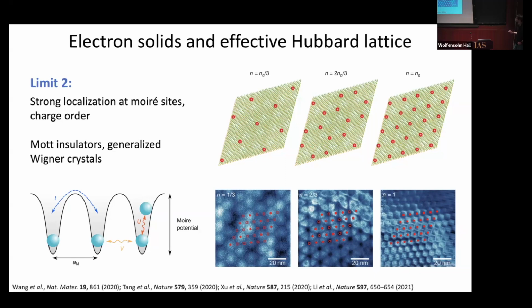That terminology comes from the fact that, just like in a Wigner crystal, this electron solid is stabilized by the long-range Coulomb repulsion. But on the other hand, here you have a Moiré potential, and so that's pinning specifically where these electrons like to sit. And in fact, there have been many examples of these generalized Wigner crystals which have been observed, and even beautiful images that you can take using a scanning tunneling microscope, where you can set yourself exactly to these different filling factors, and you can see the triangular, the honeycomb lattice, and you can see how this pattern of real space charge changes as you add carriers to the system.